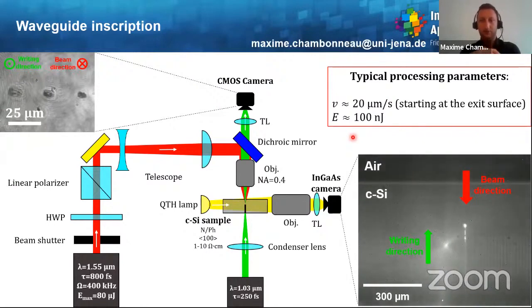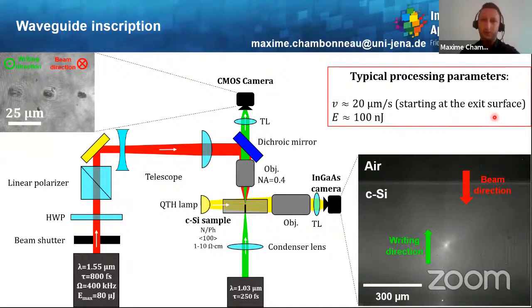So what is the trick we have found for inscribing waveguides inside silicon? Well, we start by damaging the exit surface of the sample, so creating a crater on the exit surface of the material, and then move upstream towards the laser at a constant speed. Here, typically, it's 20 microns per second and on the order of 100 nanojoules for input pulse energy. And then you can propagate and extend this crater, but you produce some strain and permanent modification inside the material by doing so.